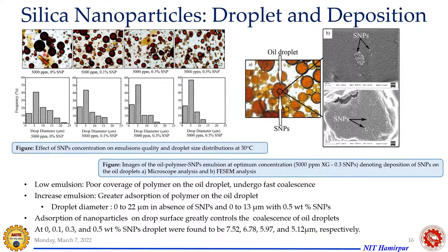So you can see here, we have analyzed this emulsion, what we have got here, and we have found out the droplet size distribution for all these properties. And you can see as we keep on increasing the nanoparticle concentration, you can see droplet diameter of 22 micron in absence of nanoparticles, but when there are nanoparticles, the droplet size reduces to 13 micron. And you can see at different weight percentage, you're getting reduced droplet size. So smaller droplet sizes are getting formed, and these are stable emulsions. So that's why it helps in diverting the aqueous stress, improving the oil displacement efficiency.